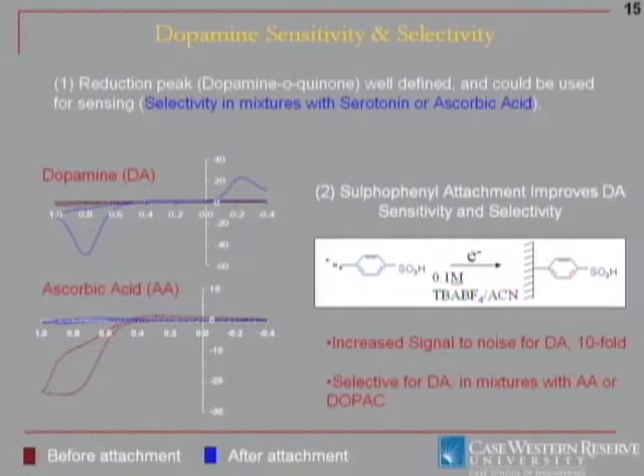And so before, we had a problem where dopamine and ascorbic acid were oxidizing in the same place. But once you add the sulfophenyl to the diamond surface, the blue scan here is the ascorbic acid signal on the diamond, and we've pretty much wiped it out. Versus the dopamine signal, actually the blue scan was after the surface modification here as well. We could see the dopamine just as well. So we have the option to either look at the reduction peaks and use that as a way for selectivity. We can also explore chemical functionalization.